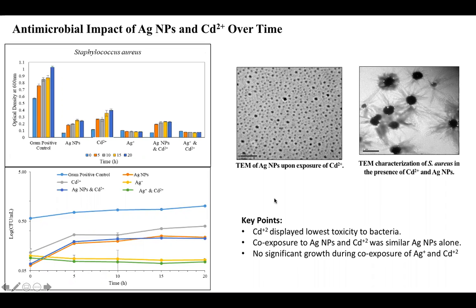Now, if we look at our TEM here, it shows 15 hours of silver nanoparticles upon exposure to cadmium. Again, we could see some broadening of those nanoparticles over time. Then we took that same nanoparticle co-exposure to look at how it attaches to the surface of Staph aureus. If we look at different points, we can see that at the surface of these bacterial strains, they're starting to break down. So it shows us that there is some attachment of those nanoparticles at that surface over time.